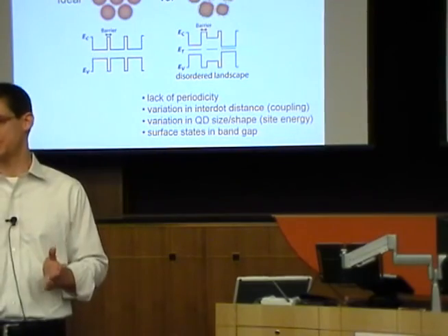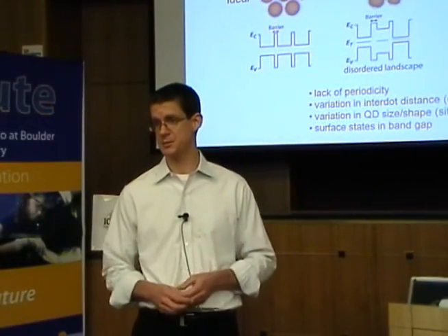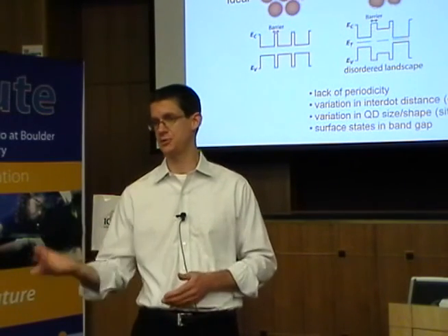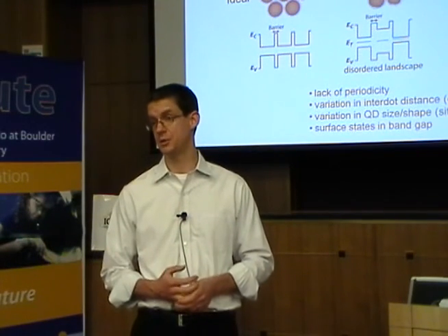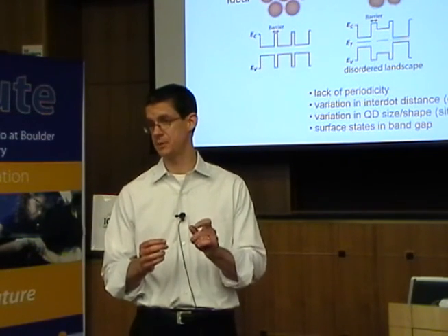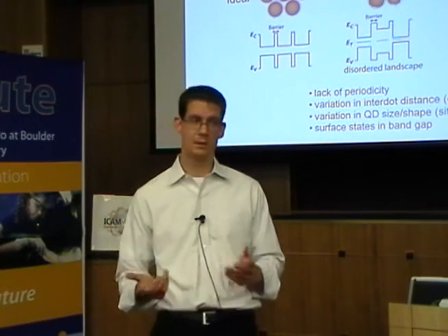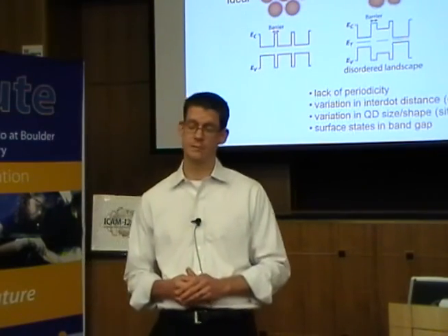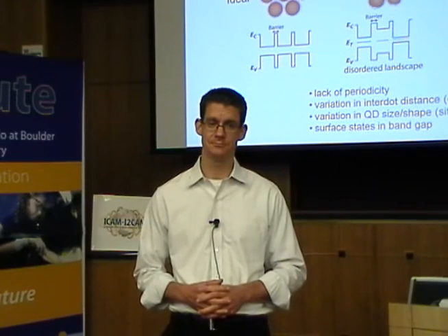That's a good question, and I don't think it's really well understood. There are a number of possibilities. One is that you can have a superposition of excitonic states and charge transfer states, and you just leak out a bunch into the charge transfer states. You can also have electric fields at the interfaces between dots that could be responsible for ripping excitons apart. You can have charge traps for one kind of charge and not the other. So the details we don't know yet, I'd say. Thank you.